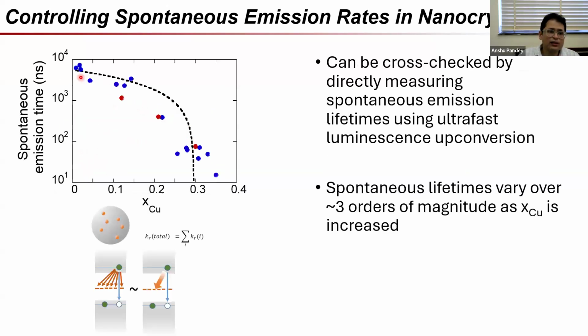So what exactly happened, and can I confirm that this is spontaneous lifetime? The answer is yes. We did it via two means. We can look at the absolute quantum yields, we find that once normalized to absolute quantum yields, in fact, as copper increases, we find a very clear-cut decrease in the spontaneous emission lifetime, so much so that we are able to tune it over 3 decades, which is a lot.